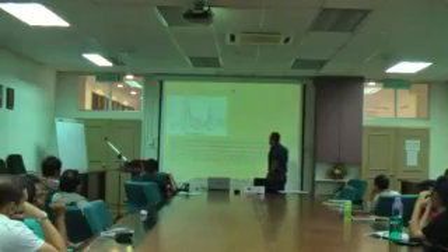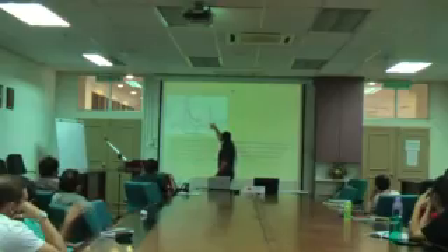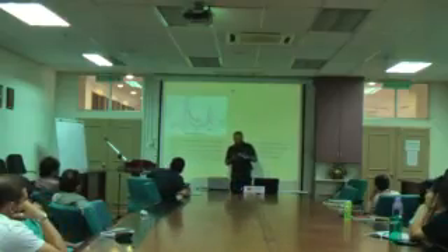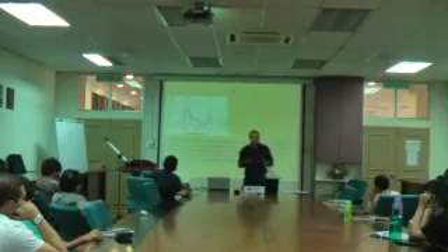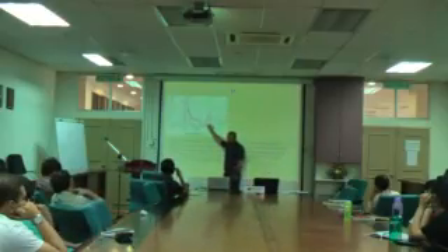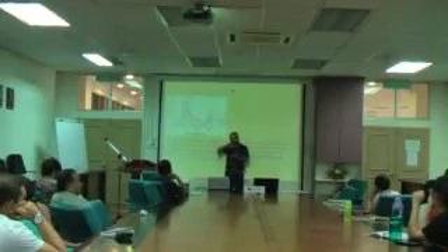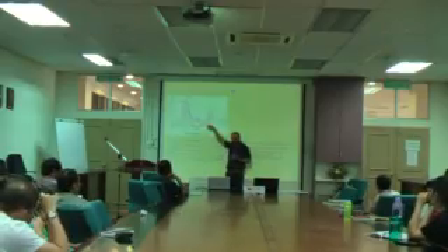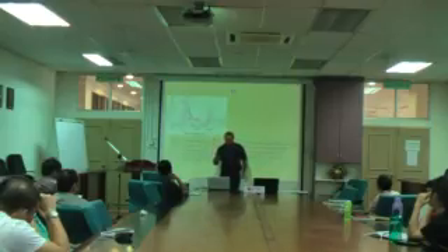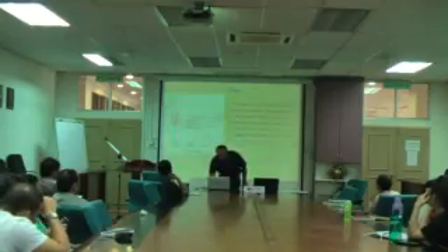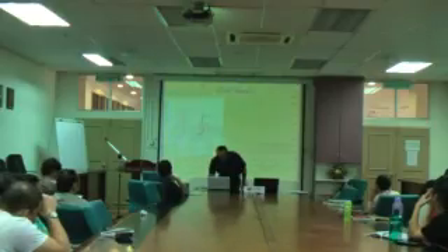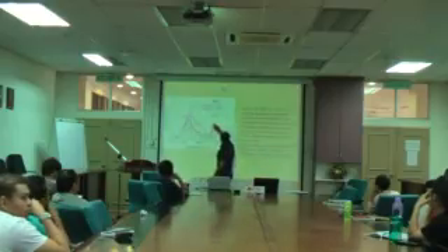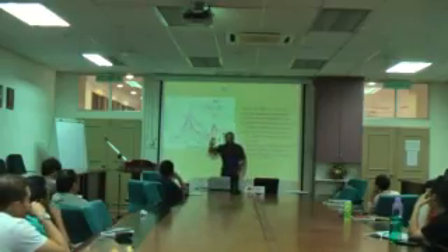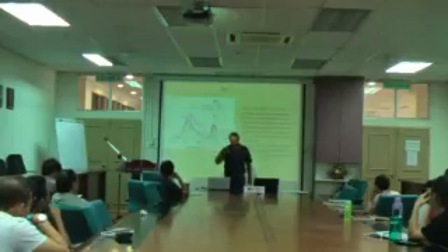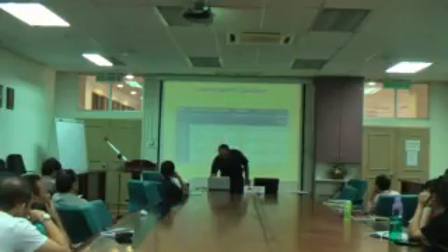So also this peaks also increases by increasing the SiO2 thickness. If you remember, this peak remains same by annealing temperature. But when we increase the silicon oxide intermediate level, this one increases. That means this one proves this argument also is true. This argument. The origination of this peaks is from this one to this one. Because when we change this thickness, that one changes.